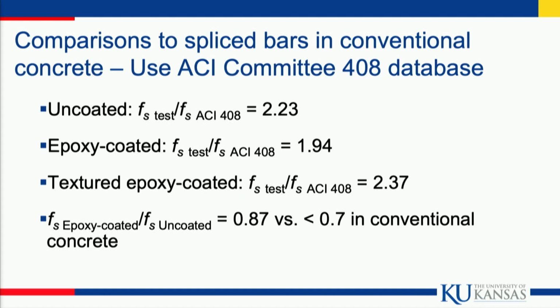Comparisons to spliced bars in conventional concrete. There's a large database maintained by ACI Committee 408, and they have a best fit equation. If we take a look at uncoated bars, the ratio of the test stresses that we got versus what you get in conventional concrete is more than 2 times as much. Epoxy-coated bars, interestingly, are almost 2 times as strong in the UHPC.